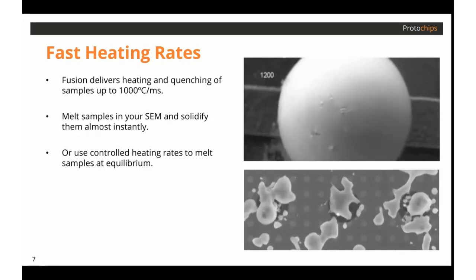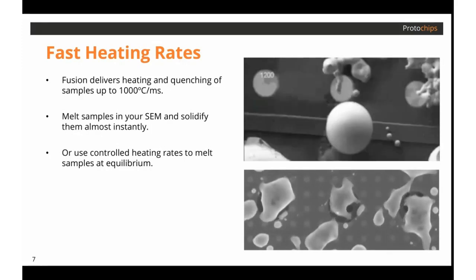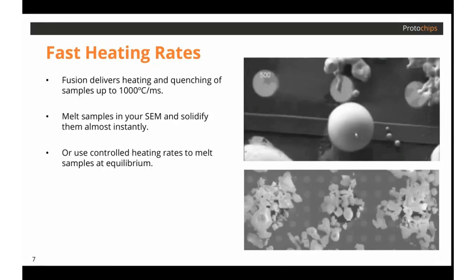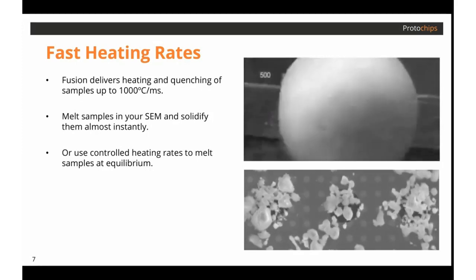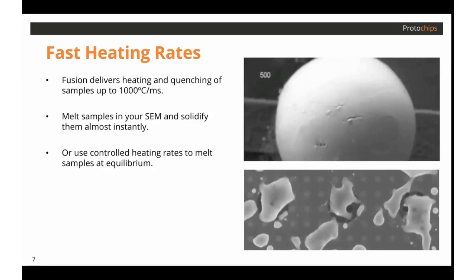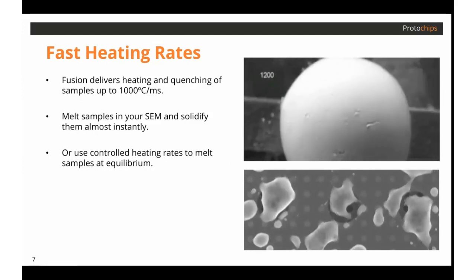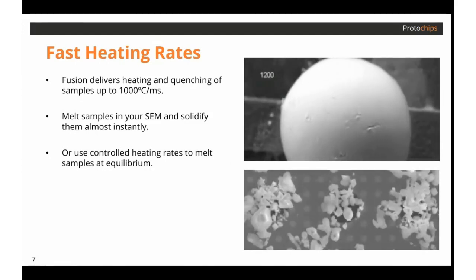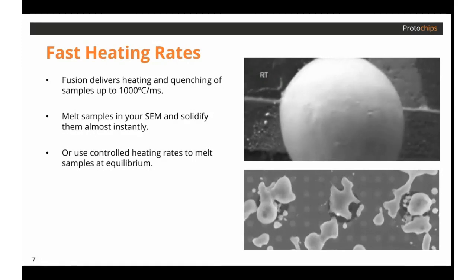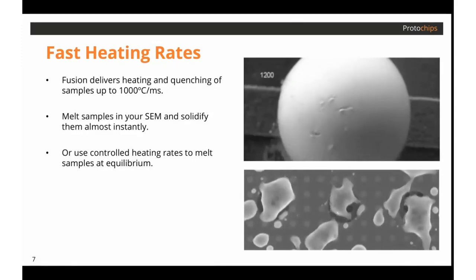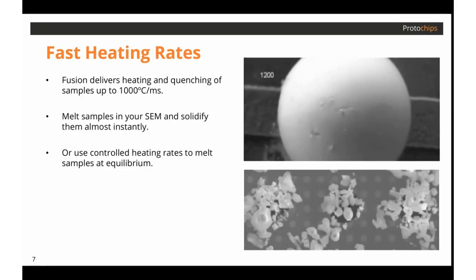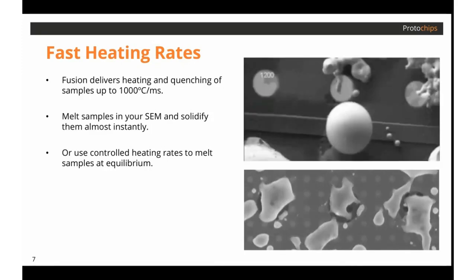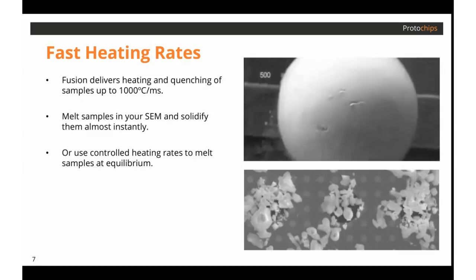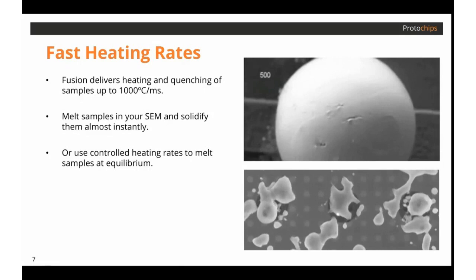In the solid state, you might be able to make out some of the crystal facets on the surface of the particle, and that gives us indication that it's at the solid state. And obviously, in the molten state, you can see thermal fluctuations showing the molten particle moving around. But you're not just limited to very fast heating and very fast cooling rates. You can also control the heating and cooling rates to whatever rates you desire.